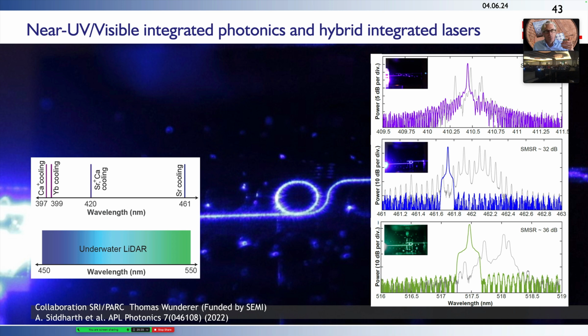Now, if you want to push even further into shorter wavelengths, I think the better material to use is lithium tantalate, because lithium tantalate is known to be also transparent down to the UV. The band gap is also quite similar, right around a bit more than 5 eV, but that's an even more promising material to push further down. So for integrated lasers right now, the shortest we can do in silicon nitride is 370 nanometer.